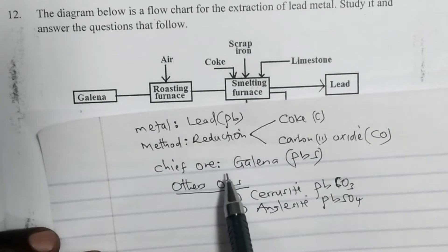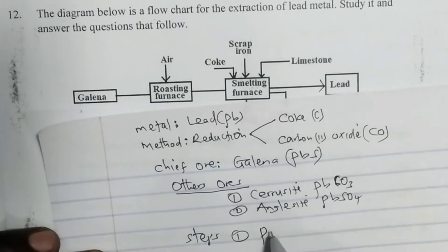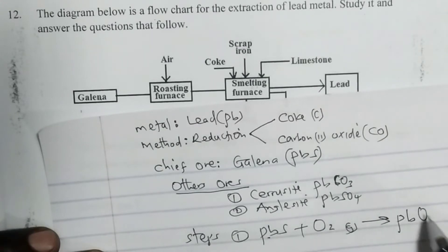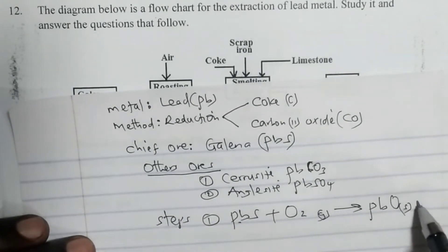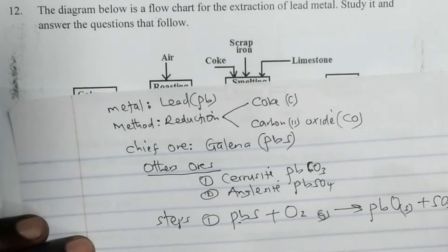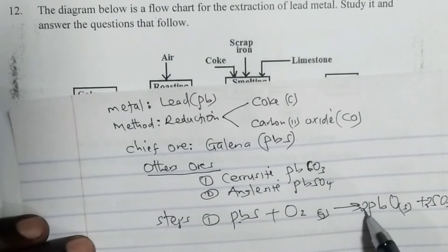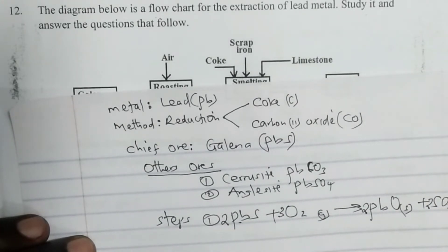The extraction of lead metal is done in two major steps. Number 1, we take the lead sulfide and burn it in air. Lead sulfide in air gives us lead-2-oxide (PbO), which is a solid, and sulfur dioxide (SO₂), which is a gas. We balance the equation by writing 2 behind sulfur dioxide, 2 behind lead-2-oxide, 3 behind oxygen, and 2 behind galena or lead-2-sulfide.